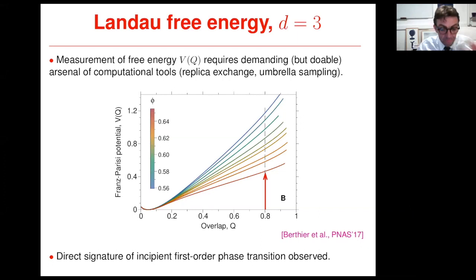So the first question we want to address is the question of the very existence of an equilibrium phase transition, of an equilibrium glassy phase of matter, based on the insight provided by the theory of the glass that I mentioned before. So here what I show are the results of the simulations where the central quantity I mentioned before, this free energy, this Franz-Parisi potential V of Q, can now be measured in computer simulation. So this is the simulation of a three-dimensional system. It's still quite demanding. It's not totally straightforward, but it's now manageable. So the figure shows the evolution of this free energy for a three-dimensional system as the system approaches the glass transition, and we go as far as we can.